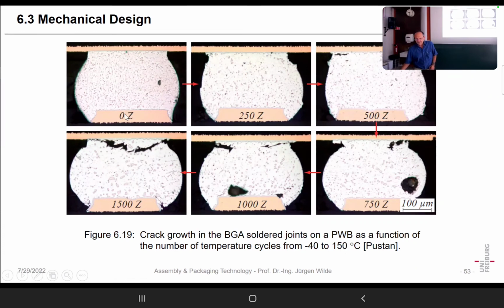And here you can find, for instance, 0 cycles that looks fine, on top solder mask defined, on bottom non-solder mask defined. At 250 cycles, it doesn't look smooth anymore because we have some internal deformation, and that leads to so-called surface kinks. These kinks accumulate, you see it already here, to cracks, mostly near interfaces, and then these cracks grow, and here at 1,500 cycles, the crack is completely through. So what's the number of cycles to failure? It is when the crack has gone through that ball, and that means, as it in most cases comes from both sides, somehow also the radius of that ball is relevant.